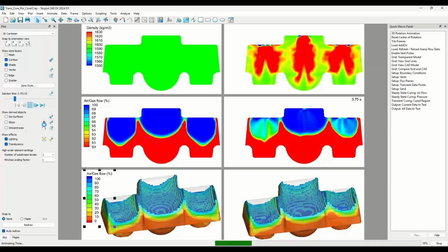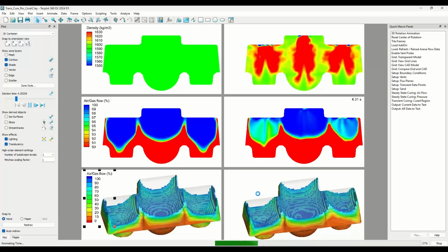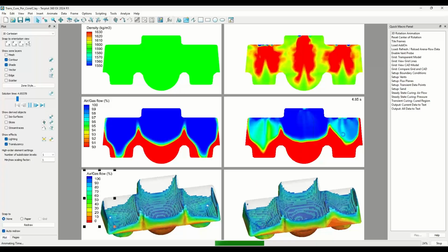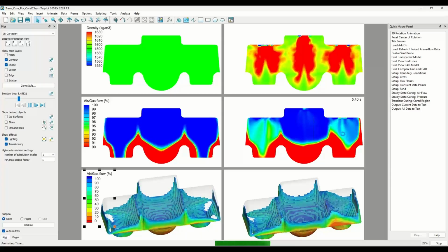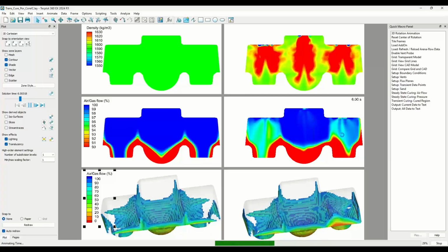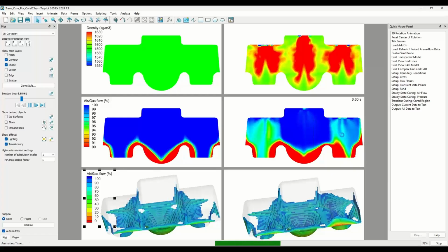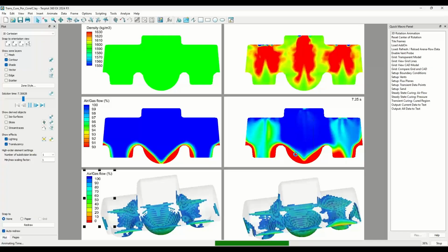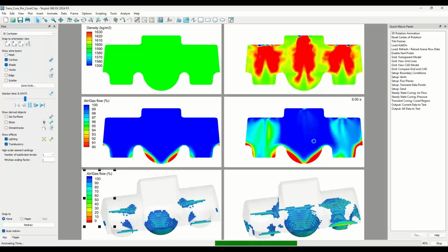You see, they are pretty similar, except that we can see how the two side areas in the core where we actually use the density, the particle volume fraction from the blow for the porous media definition, is showing slower to cure areas.